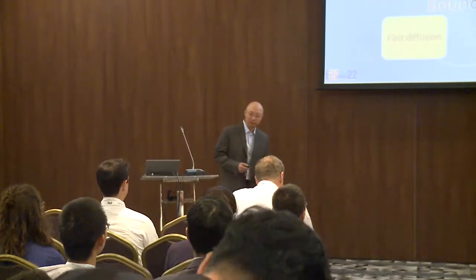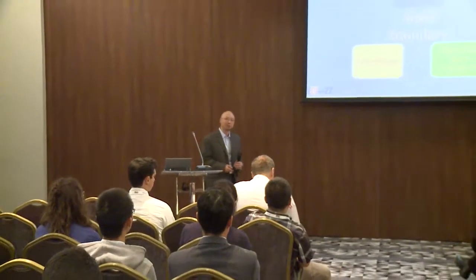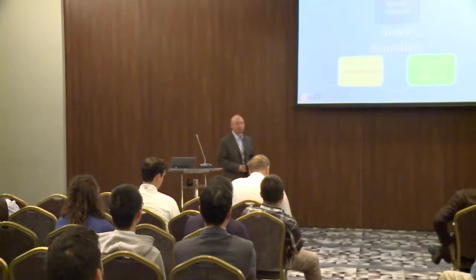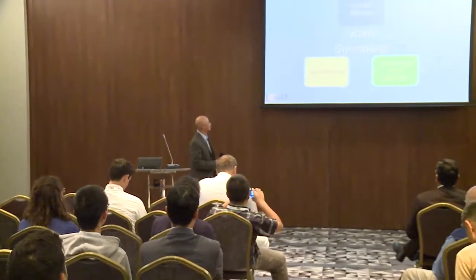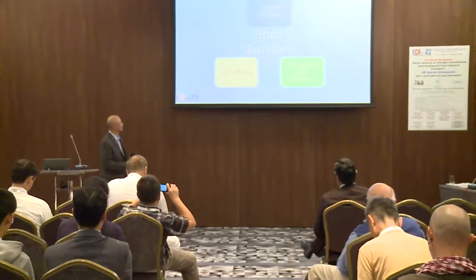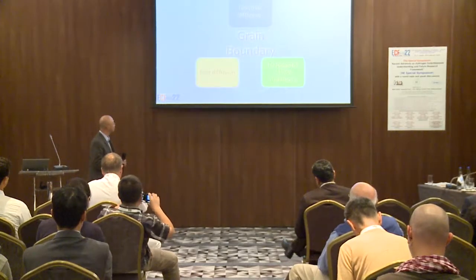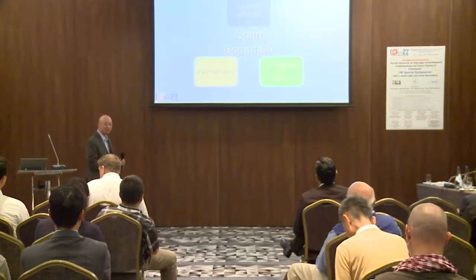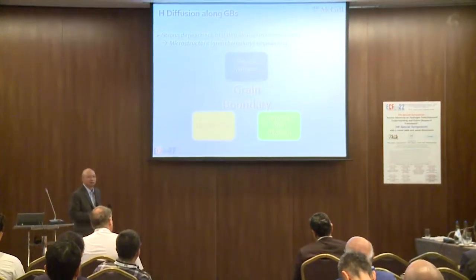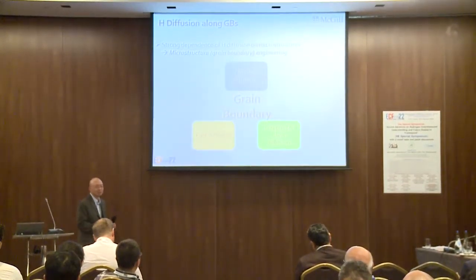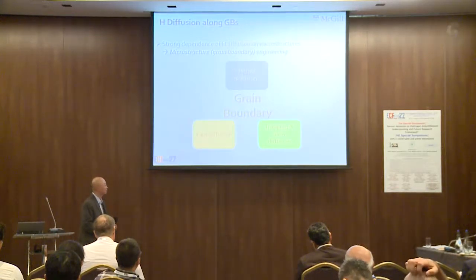But I will make a mention of the tools we recently developed, which can also characterize the energetics of it. Okay, so as many literature studies suggest, grain boundaries are important entities for affecting the hydrogen environment. In particular, from the diffusivity perspective, there have been studies supporting trapping and slow diffusion, or some studies suggesting that grain boundaries facilitate diffusion, or some studies showing that you actually expect a normal diffusion. So there's nothing changed with or without grain boundary.